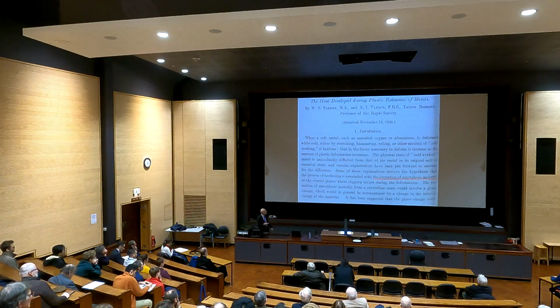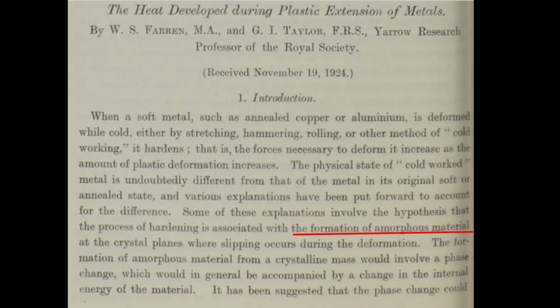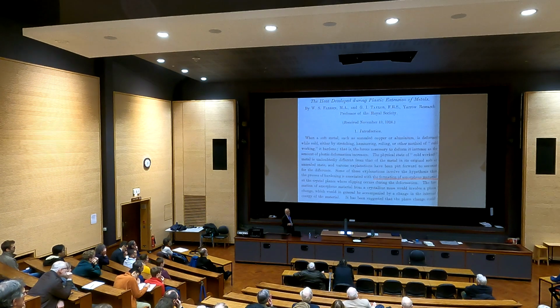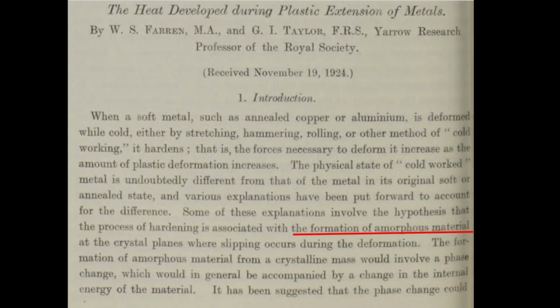Their one assumption, a prominent assumption, was that when you slip these planes, of course, it in some way disrupts the crystal structure. And they assumed that you could have formed layers of amorphous material between the slipping planes. And that would act as a sort of gluing up of the system that wouldn't allow them to slip. We now know that that's not the explanation of what he was seeing, but you can actually do this. If you take a crystalline metal and you deform it heavily enough, you will eventually destroy the crystal structure and you can form an amorphous metal. But that was not what was going on in his case.